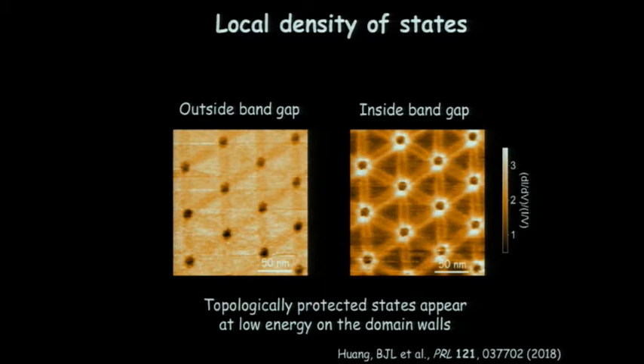So the electrons can move freely everywhere there. If you go inside the band gap, so you use a condition where you've opened a gap in the Bernal stacked region, you use low bias to probe in there, what you'll see is the dark regions, the Bernal stacked regions, have low density of states, they're gapped. And there are these two lines that connect along each of the AA vertices. These are the topologically protected states running between the AA sites along the domain walls, always connecting the AA sites.